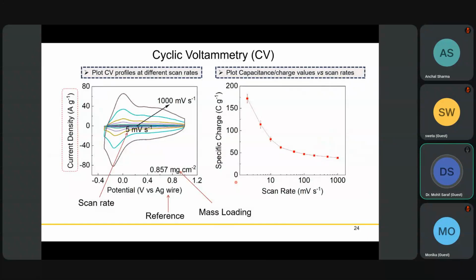Once you get your cyclic voltammogram, you get curves where the y-axis shows current and the x-axis shows potential. It's important to always mention which reference electrode you are using; for example, here we were using a silver wire, so it's important to mention which kind of reference electrode is there. When you get the current, you have to divide it by mass to get the current density. This division is very important when comparing different systems. You can also present the current alone, but when comparing different systems, you have to present it as a current density.